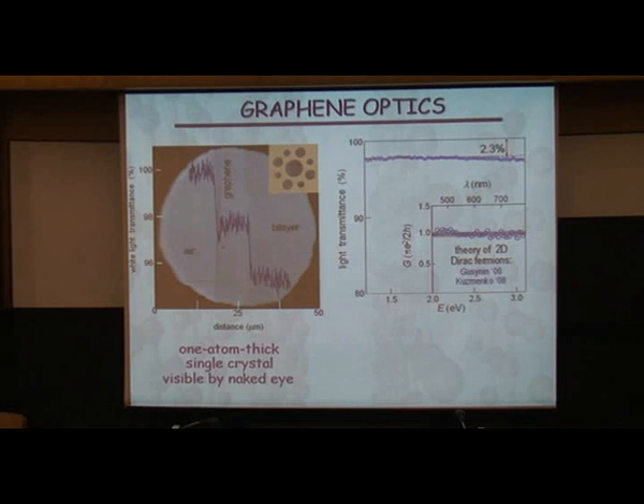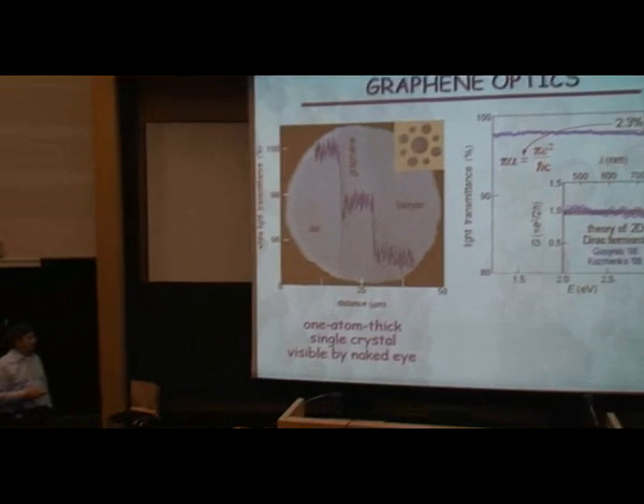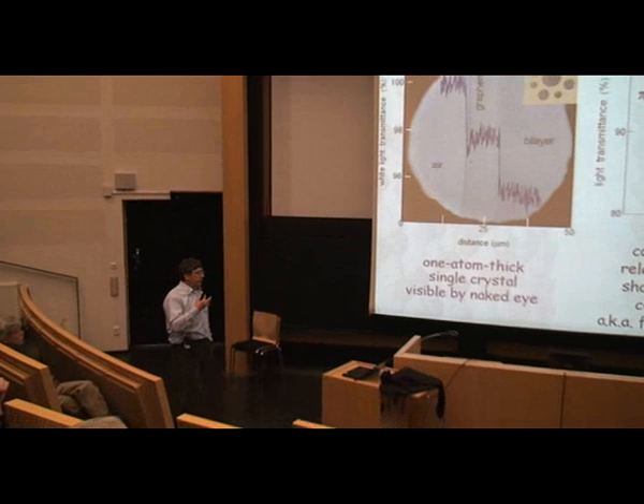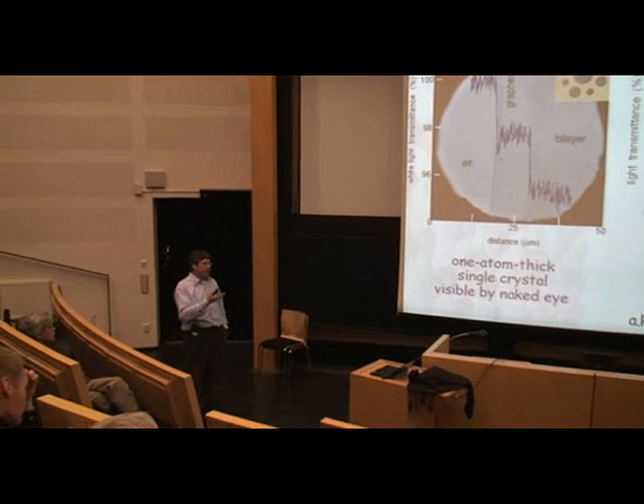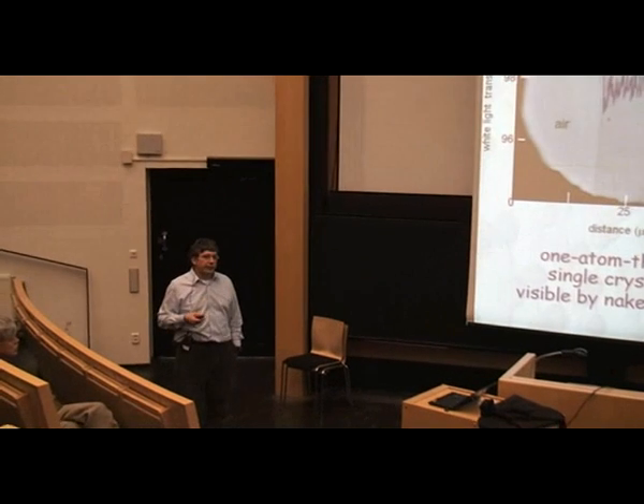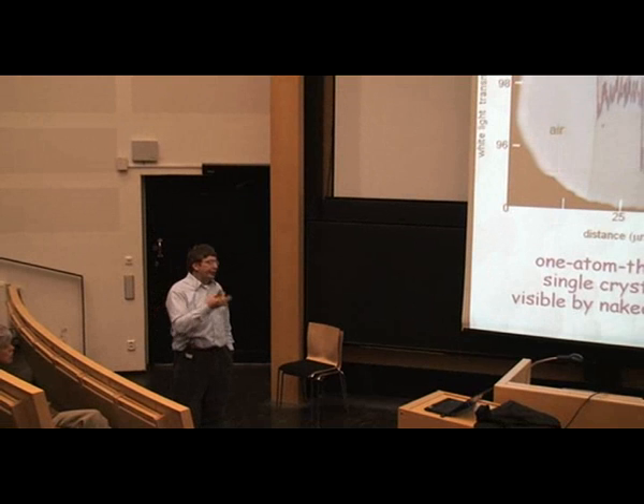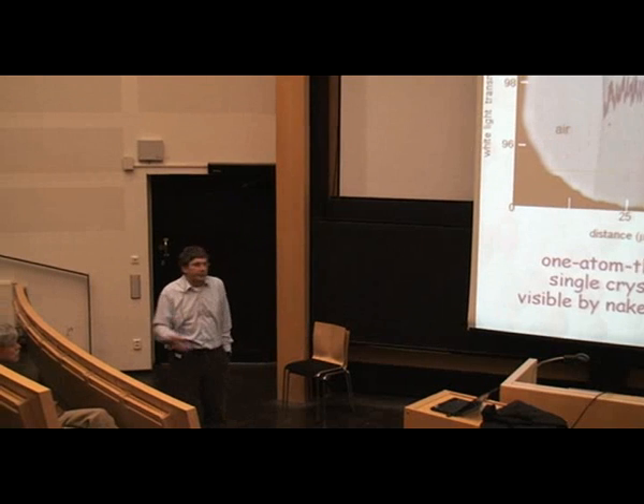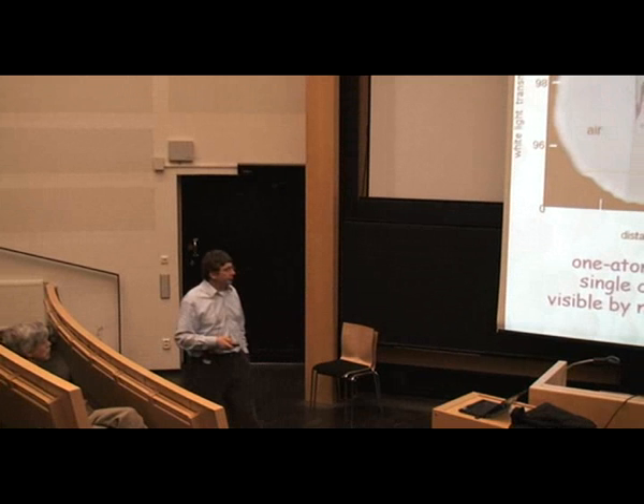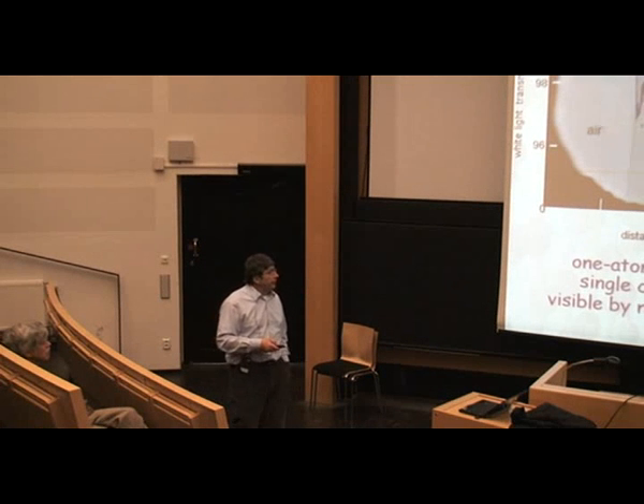Again, it turns out to be a conductivity of the order of e squared over h, and this 2.3% actually then translates to a quite meaningful number, which is pi times the fine structure constant, the real fine structure constant. So in this experiment, essentially by the naked eye, you see not only the material, the thinnest you can imagine, but you probe the fine structure constant. I try usually to trivialize, as an experimentalist, all the observations, and you can really think why it's happening, why the fine structure constant is important, because in this experiment you probe the interaction, coupling of light with relativistic charges, and this coupling should be described, of course, by the coupling constant, and the coupling constant is also known as the fine structure constant. This is an intuitive description of this experiment.